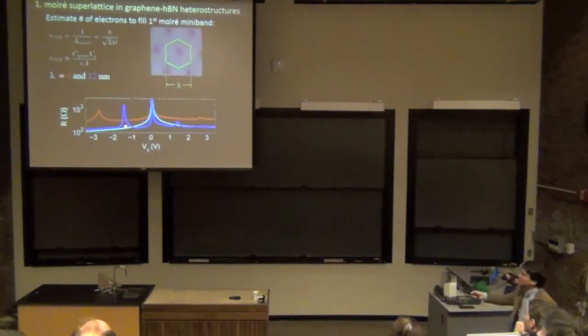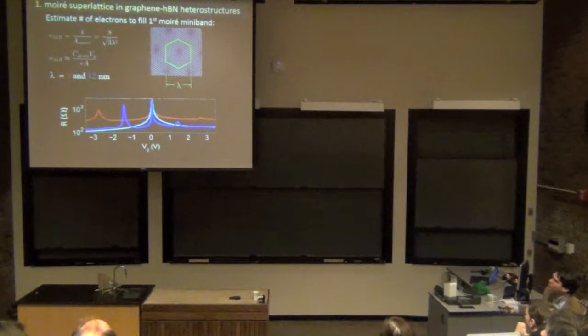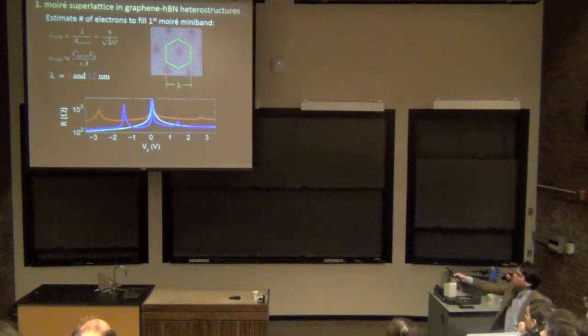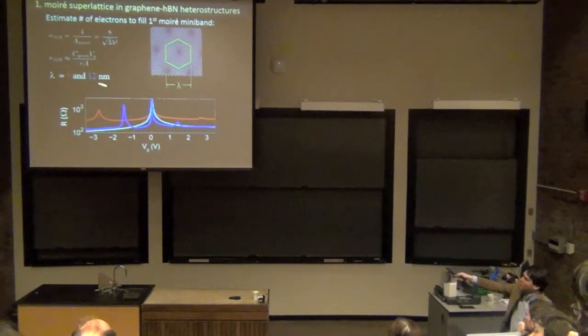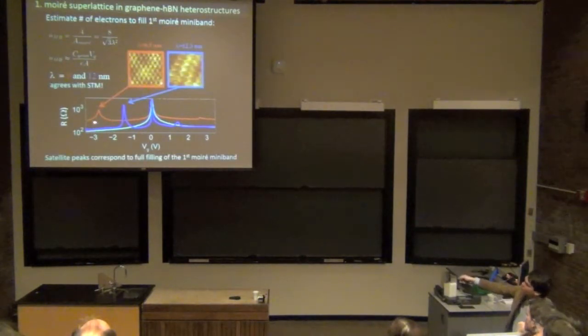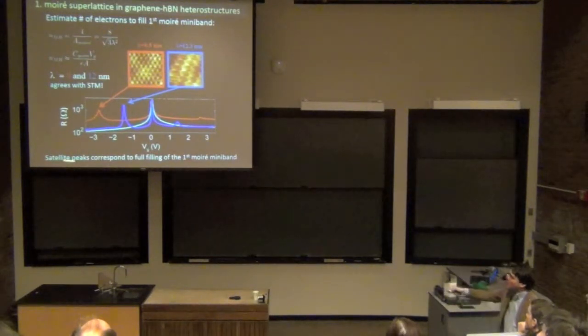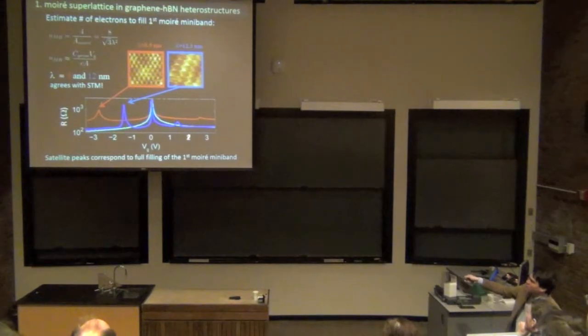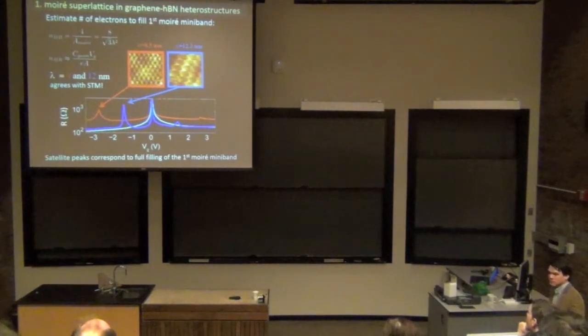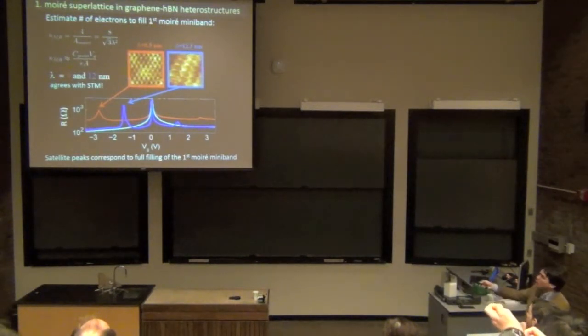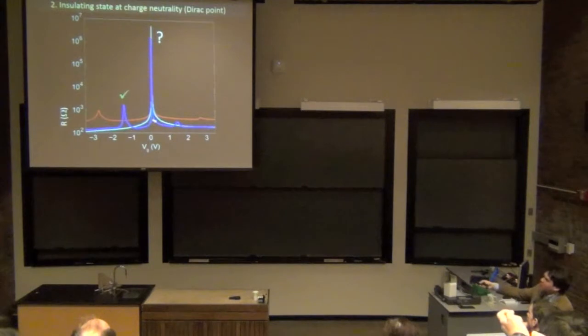And we can actually verify that these satellite peaks are coming from the moiré by basically estimating the number of electrons that it takes to fill up one of these moiré minibands. So you can just use an electrostatic model, predict what the wavelength should be, and compare to STM, and you find out that indeed these numbers compare pretty well. So we're pretty confident that these satellite peaks correspond to some description of the electronic structure of graphene getting modified. Okay, so we understand these satellite peaks.